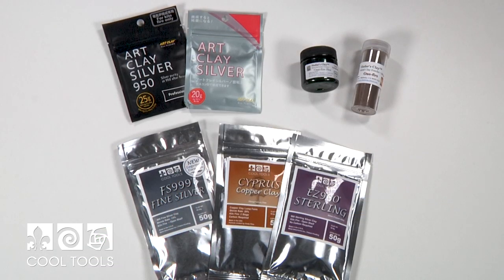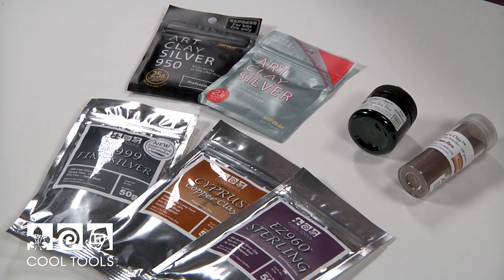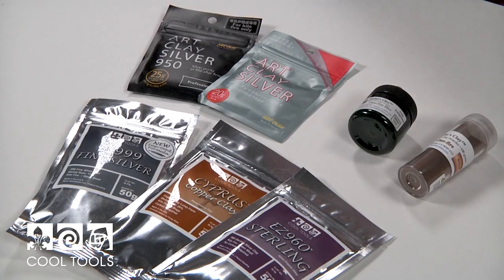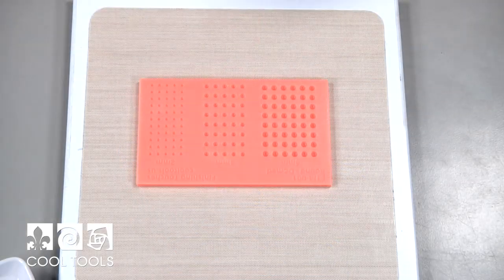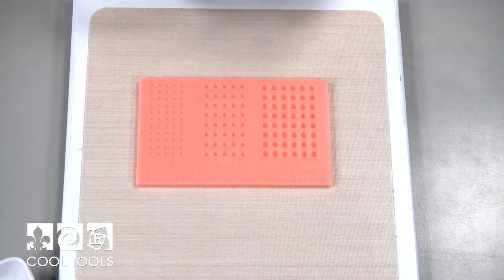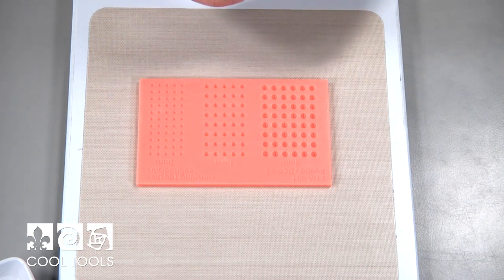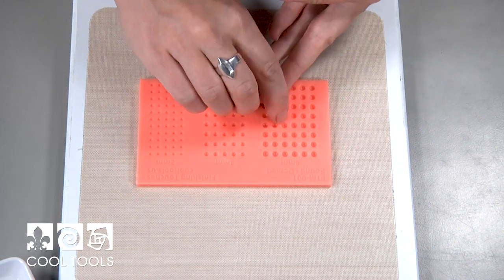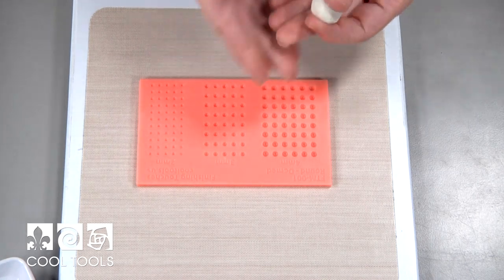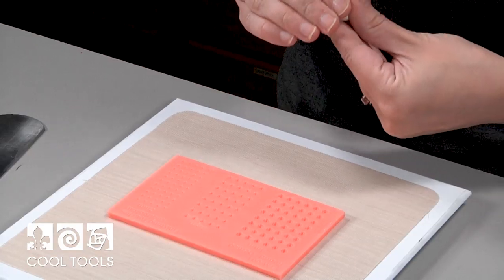I've done quite a bit of testing with different clay bodies to see which perform best in these molds. Art Clay Silver does well in them, and Hadar's clay performs beautifully in them as well. Also, our Cool Tools brand clays perform very well in these molds. Unfortunately, I did not have very much success using the PMC clay bodies as they would peel out instead of staying in the low areas. So for this project, I am using fresh clay, and it's important that you're using fresh clay because if you're using dry clay, you might get little cracks on the surface where it's not able to smoothly and evenly get down into the mold.